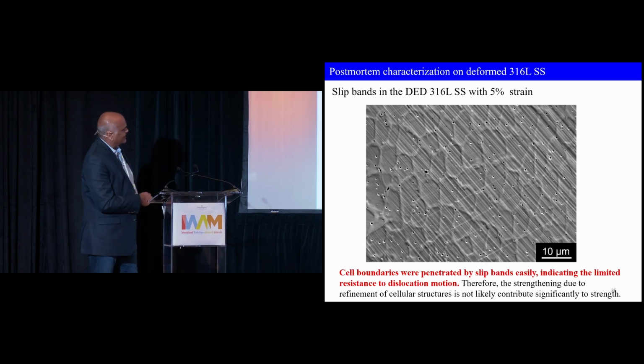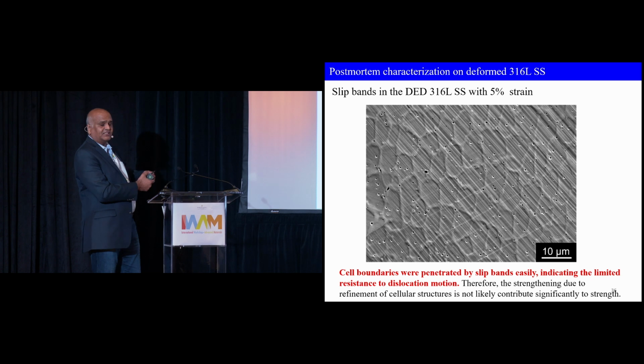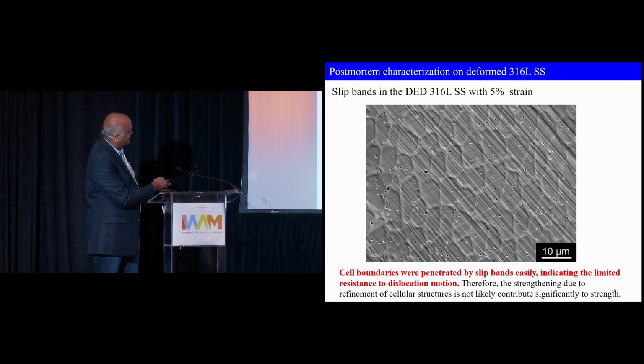But the cellular boundaries really don't stop dislocations, and that is what this picture shows. This is a well-polished tensile specimen. We applied 5% strain on it and looked afterwards. Don't focus on these dots - these are silica particles, they don't really contribute to the strength.